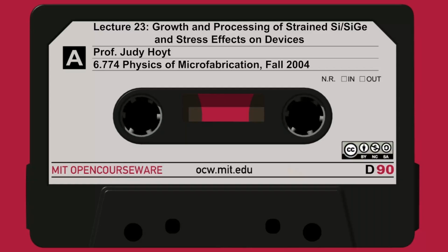And on slide 15, he actually measured some of those mobilities. These were the first mobilities measured. If you look at this solid line, this is the mobility measured in a MOSFET that had no strain. For a surface channel MOSFET, the mobility that he measured was about 80% higher, about a factor of 1.8 improvement. So right off the bat, as a function of vertical field, by changing the strain, you can up the mobility by about 80%.